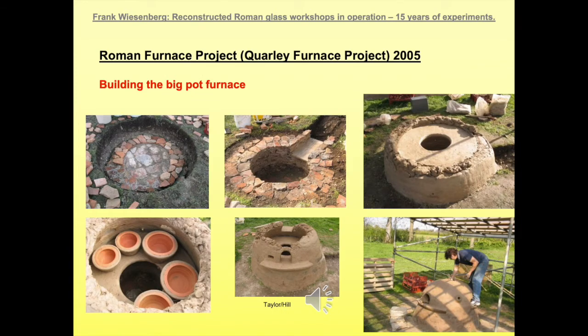Here are a couple of shots of building the big pot furnace. The furnace floor is laid out with Roman roof tile fragments, pretty large fragments, and covered in daub. It features an inner shelf where the pots are located. The pots in this very early stage of the project were covered in a layer of daub, which is made from just local loam and some vegetable matter. The dome is closed bit by bit to have an almost closed top of the furnace, which contains the heat very well.